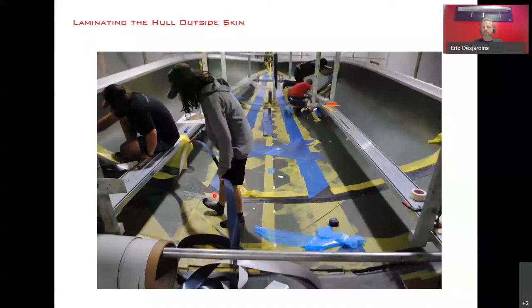So a block of steel, if it's not forged, has the same mechanical properties in all directions. It's isotropic. Well, with composite material, you can really design the material to match the requirements of your structure. So you've got designers going to great lengths about, oh, I want this fiber to be at plus minus 46 degrees and this one at 83 degrees. So they keep us on our toes when we lay up all this fiber.